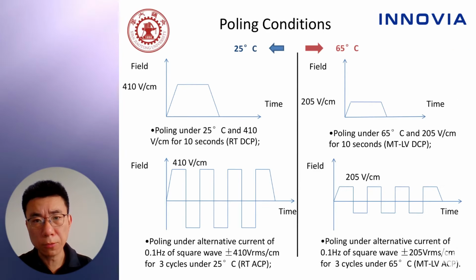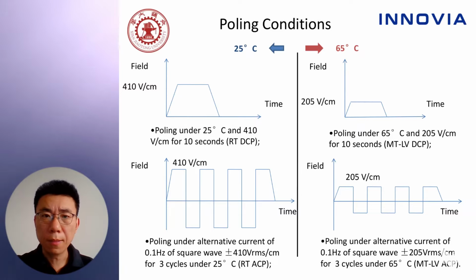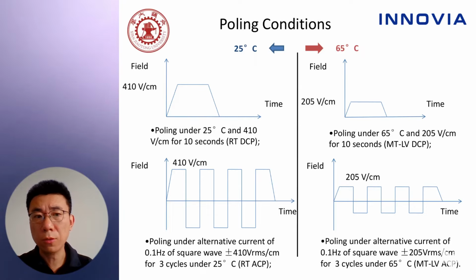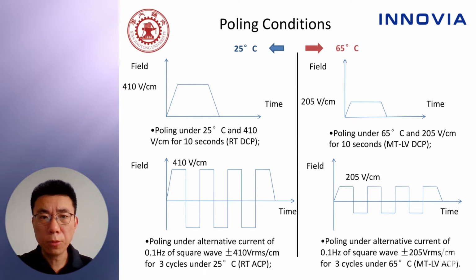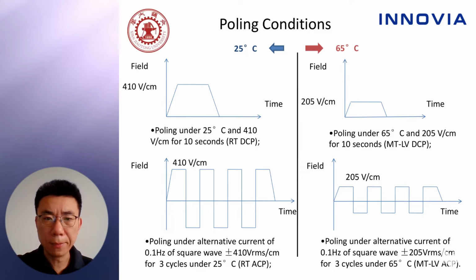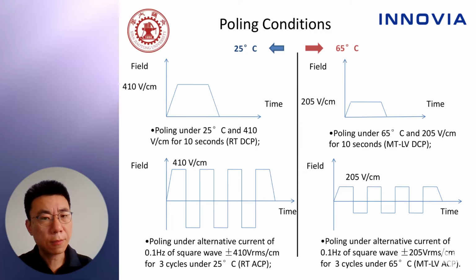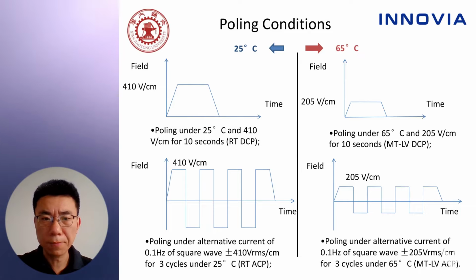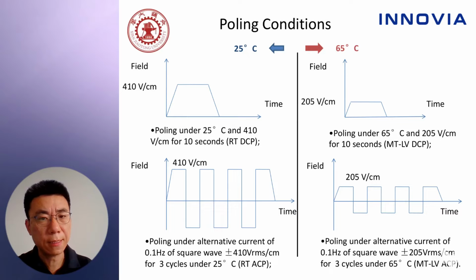There are 4 conditions we proposed in this study. The 2 conditions on the left of the screen are poled under room temperature, and on the right of the screen are poled under 65 degrees Celsius due to ease of fabrication. First condition, poling under 25 degrees C and 410 volts per centimeter for 10 seconds, RT-DCP. Secondly, poling with an alternating current of 0.1 Hz square wave plus minus 410 volts per centimeter for 3 cycles at 25 degrees C.